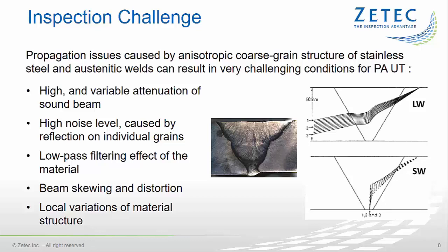For example, the attenuation of the sound beam is high and variable. Also, we will typically see a high noise level because each of the large grains will act as a reflector for the sound wave. Then there is the low-pass filter effect. This means that the austenitic material will put a limit on the frequencies that can effectively propagate through it. This will drive us to use lower frequency probes. The ultrasonic beams will change direction and will be distorted by the individual large grains. And finally, as if the previous challenges were not enough, all phenomena will vary depending on the location of the phased array probe along the weld.